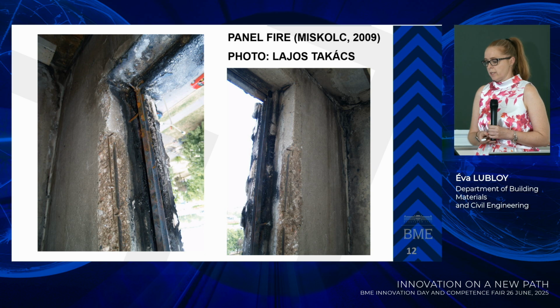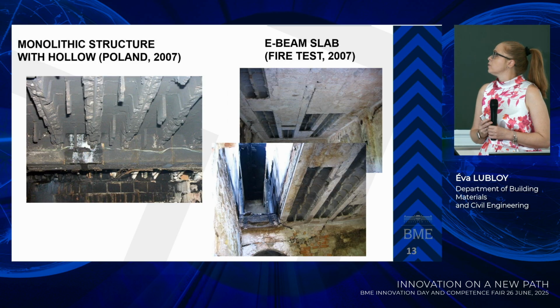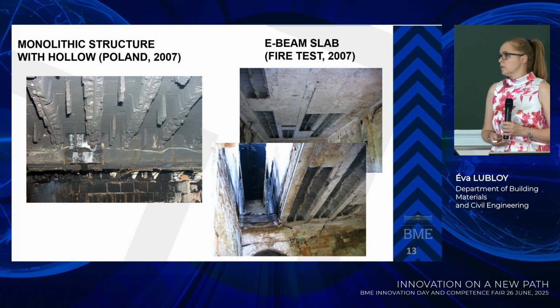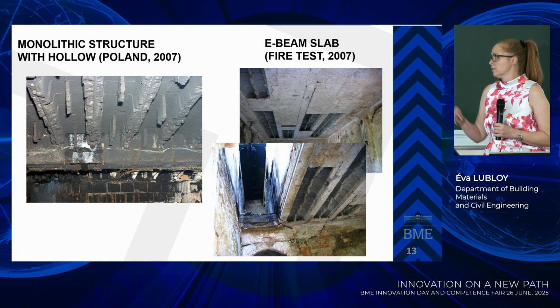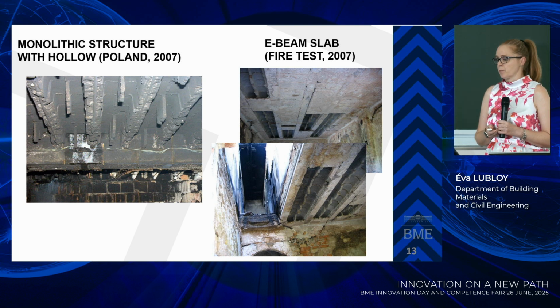What happened with concrete structures? Yeah, I think swelling of the corners is not dangerous. It's not good, but it is not really dangerous because we are not damaging the load-bearing structures. But in this case, if you have hollow core slabs, then the underside can collapse, and we can have some problems with hollow core slabs. Hollow elements are really dangerous in fire because we have other heat effects inside these holes.